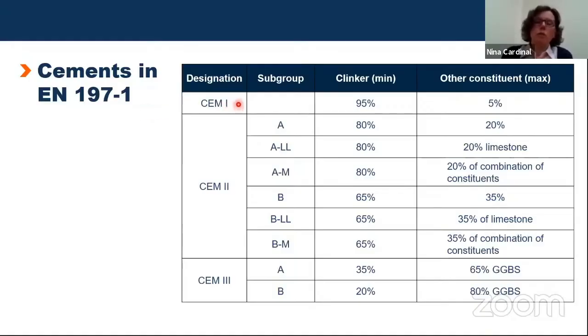So I've chosen 3 common groups here, CEM1, CEM2, and CEM3. And CEM1 is what probably most of you are familiar with, Portland cement, which consists of 95% clinker as a minimum and a maximum of 5% of other constituents. The CEM2s are currently divided into 2 groups, CEM2As and CEM2Bs. The CEM2A cements allow up to 20% of other additions. So for example, a CEM2A-LL can have, in addition to the clinker, up to 20% limestone. And a CEM2A-M can have a combination of other additions up to 20%.